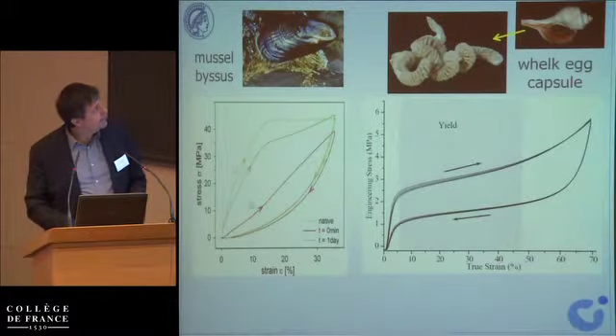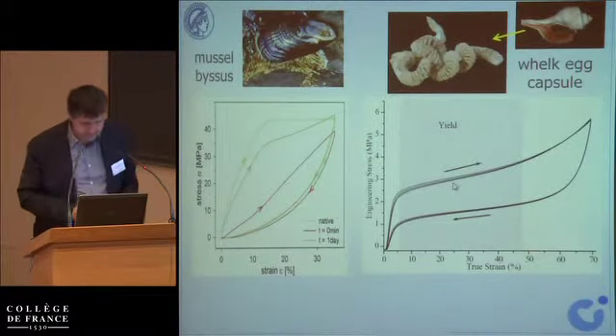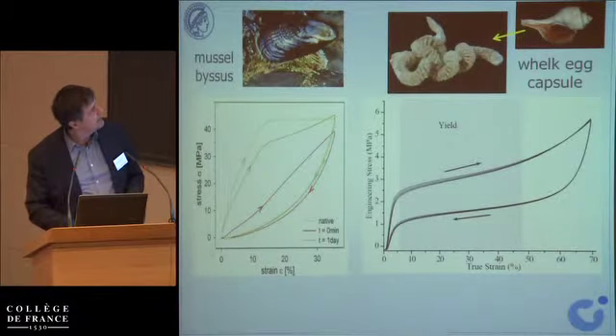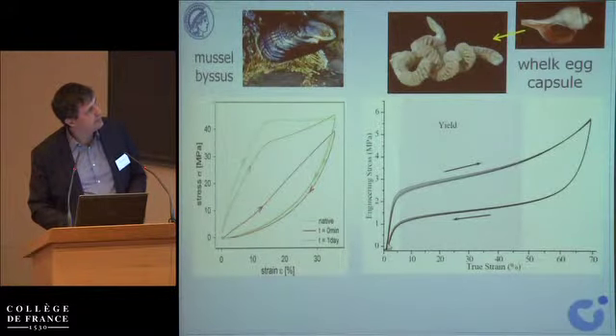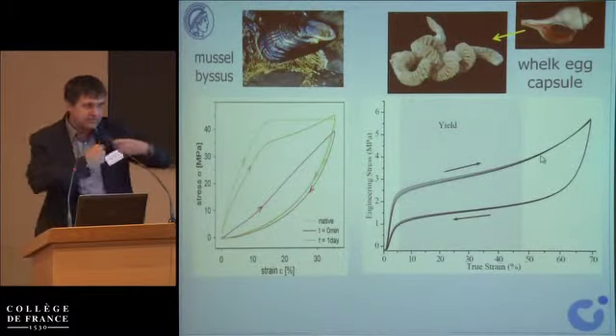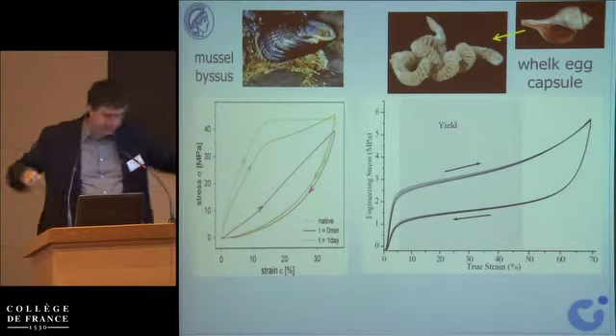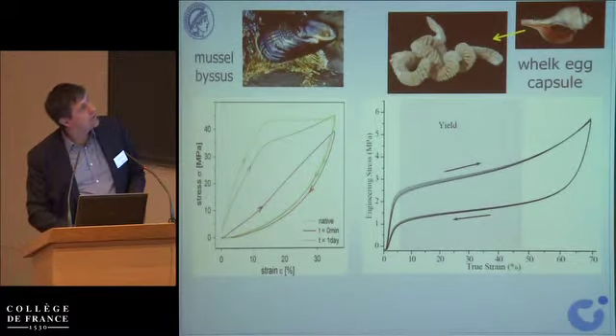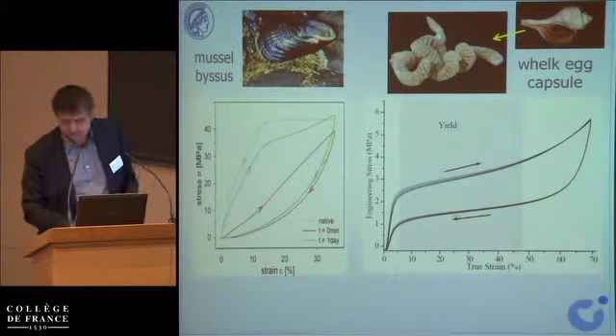The stress-strain curves of these materials are shown below. This is the load that's applied, and this is the strain. And you see these things have cycles. Well, let's look at this material, for example. It's fairly stiff if you start to bite on it. If you bite sufficiently strongly, it starts to deform like crazy, but it doesn't break. It deforms 50, 80%. So with your steak, you bite into it, it deforms, it doesn't break. You stop biting, and it just comes back, and then you bite again and again and again, and it just doesn't break.